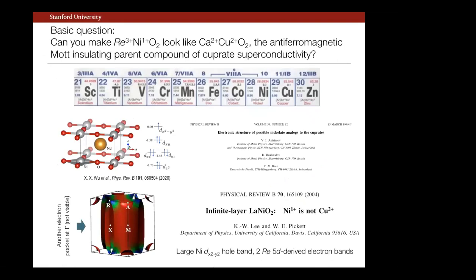So the basic question is rather simple, which is, can you make a nickelate structure look like the cuprate superconductors? In particular, you can see, for example, that nickel is one over on the periodic table. So specifically, if you can make something like a rare earth 3+ nickel 1+ O2, this should be isostructural and isoelectronic to the so-called infinite layer cuprates, say calcium or strontium copper oxide.